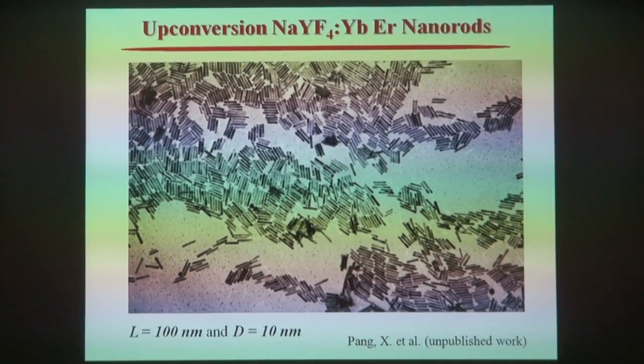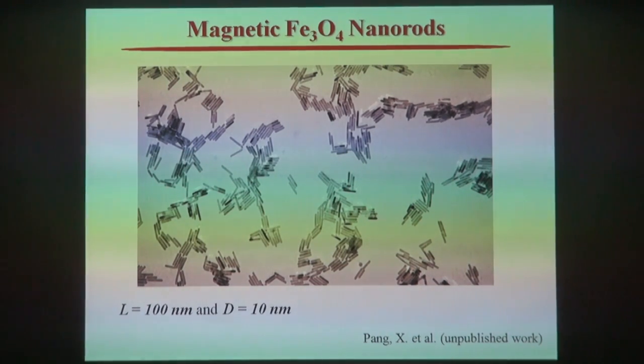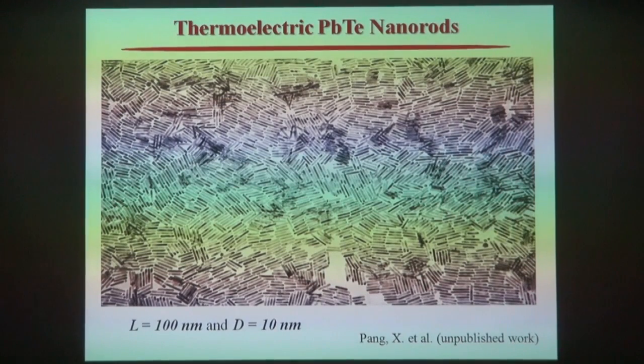So they absorb low energy and they pump out high energy. And also, by being able to absorb near IR photon, they allow you to do a lot of bioimaging study using these particular nanorods. Here, again, by using the same bottle brush like copolymer, you can make magnetic iron oxide nanorods of identical dimensions. We are talking about identical aspect ratio, identical length and diameter, but different materials. Magnetic iron oxide nanorods has not yet been demonstrated in literature in terms of making uniform nanorods for magnetic iron oxide. If you continue marching on, to use different inorganic precursors.